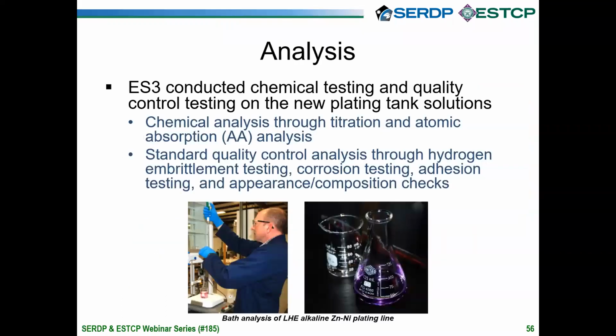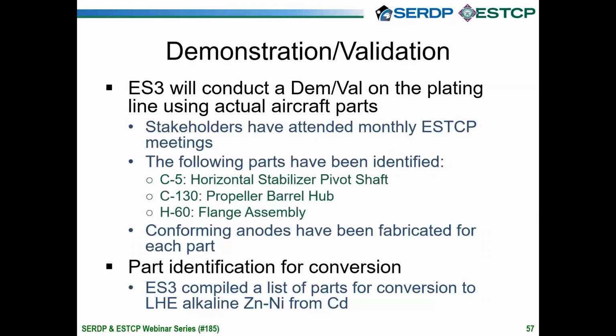You can go on to slide 56, Greg. So some of the analysis that we performed already and that they performed on base, titrations, which would be done more for the molecular components like sodium carbonates, and then all of the elemental analysis is typically done, at least at ES3, with the AA atomic absorption spectroscopy. Then after everything is in quality from a chemical analysis standpoint, we'll perform the test that you see in that last bullet there. Next slide, Greg, 57.